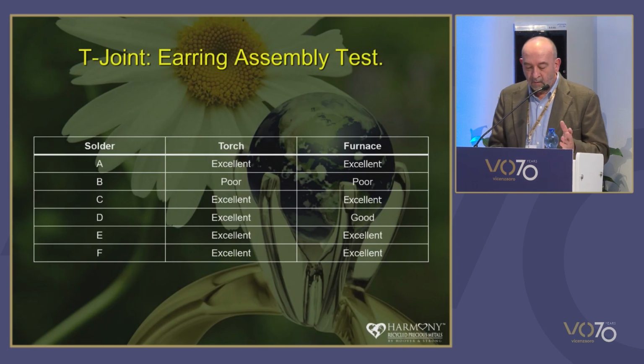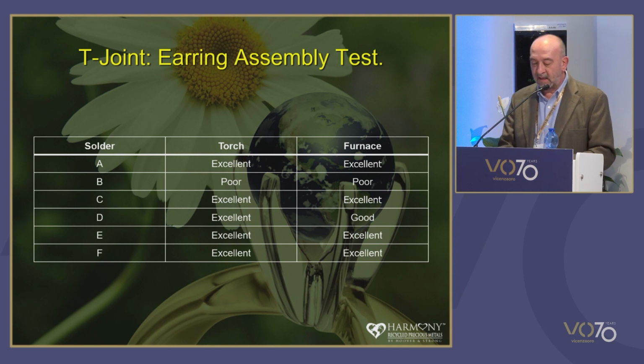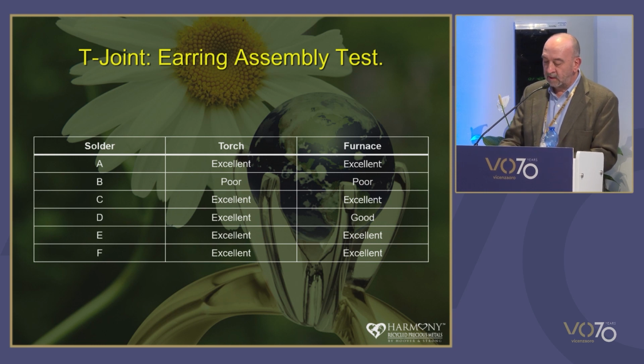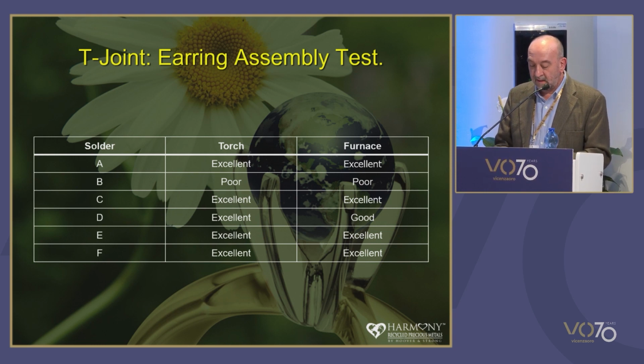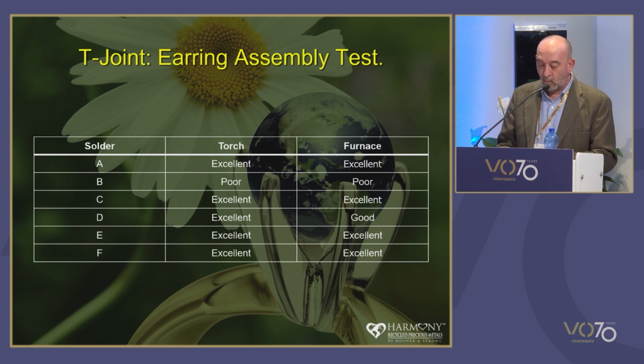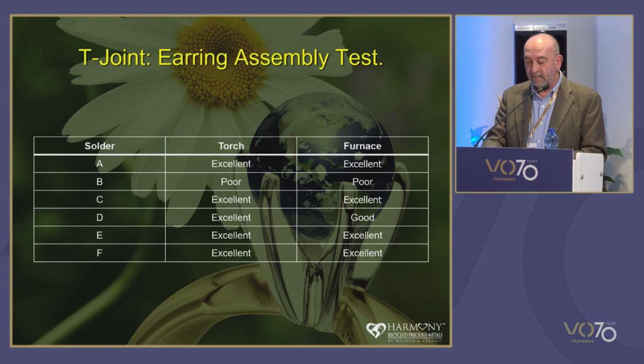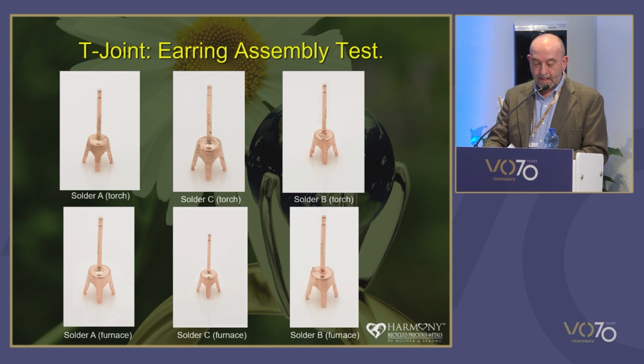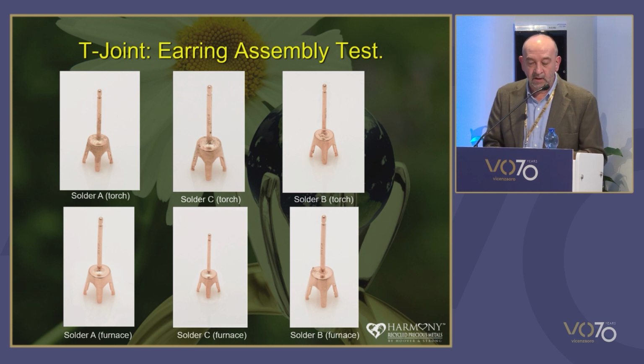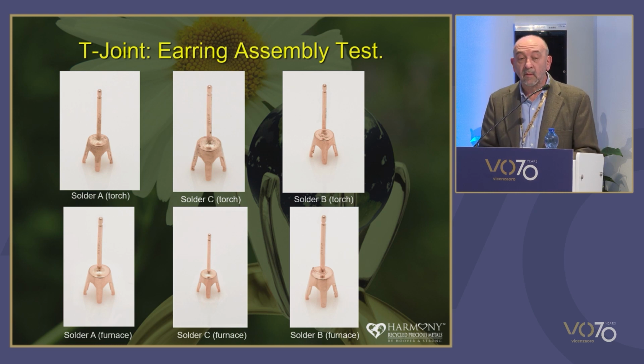Unlike the ring sizing tests, all earring tests gave similar results for both torch and furnace soldering, and there was a negligible difference between any cadmium or cadmium-free solders. And again, all except solder B performed well, exhibiting good wetting and good filled joints. These images show you, up there on the top left, solder A, either with torch or furnace, soldered very, very well. Solder C was the cadmium-free version of that solder. Again, soldered very, very well. But solder B was awful in both applications.